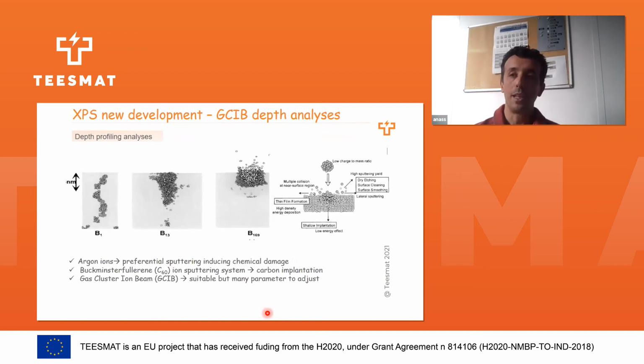The second way of depth profiling is what we call ionic depth profiling. Here, there are two kinds of depth profiling: either ionic depth profiling or gas cluster ion depth profiling. Here is the ab initio molecular dynamics simulation of two kinds of ionic sputtering. This is monoatomic ion sputtering. These are argon atoms accelerated to 20 kilovolts into some kind of sample. We can see that when we do etching, the argon will penetrate deeper in the material with lots of cascade interactions. So that will generate chemical damage to our sample.